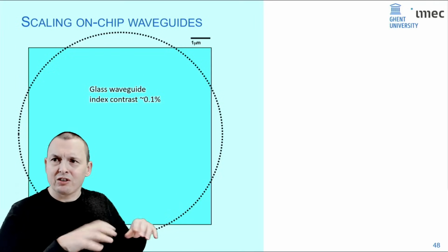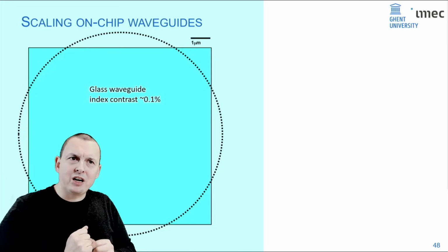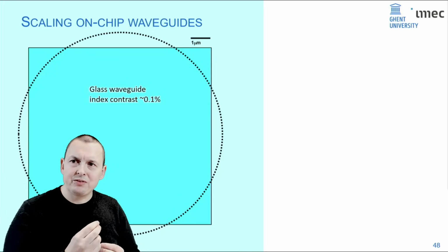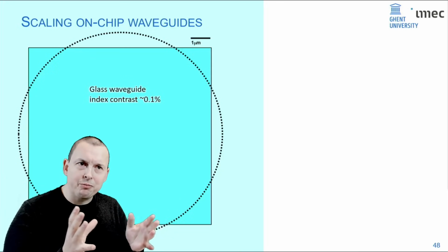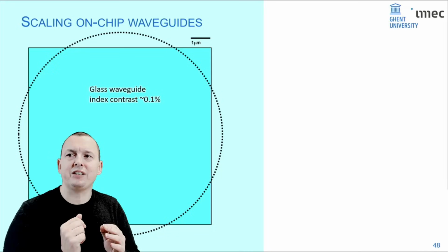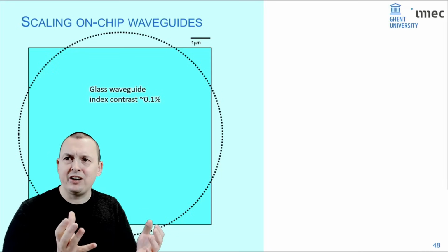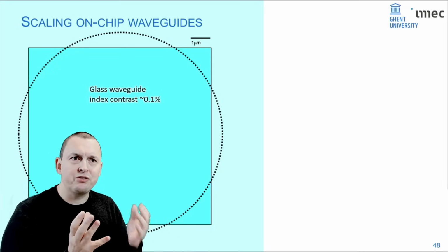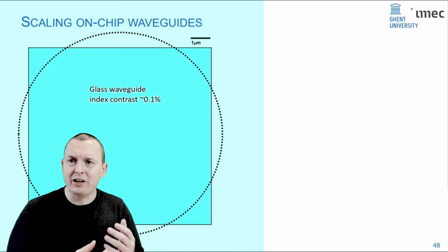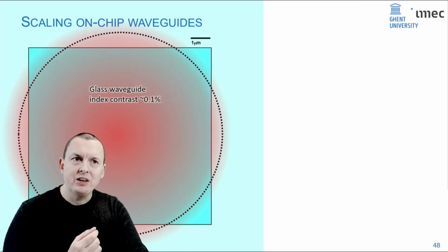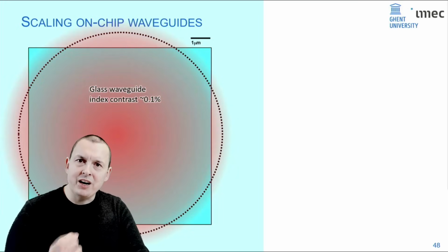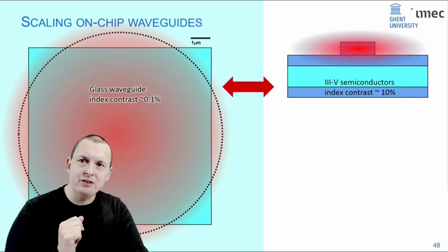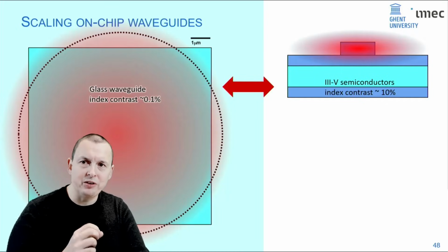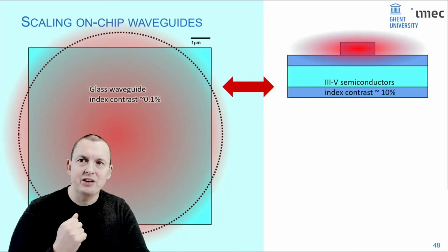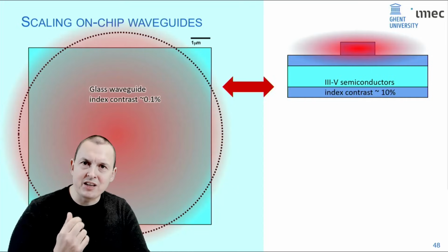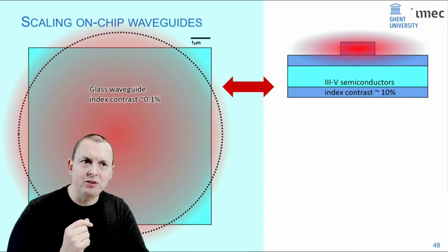You see, when you make a waveguide out of glass, like an optical fiber, which is surrounded by another type of glass with a slightly smaller refractive index, you get fairly large waveguide cores, on the order of 10 micrometer, in order to guide the light efficiently. Now, if you go to materials with a higher refractive index contrast, like for instance III-V semiconductors, where you can have an index contrast of 10%, you can scale your waveguides down to a scale of a few micron.